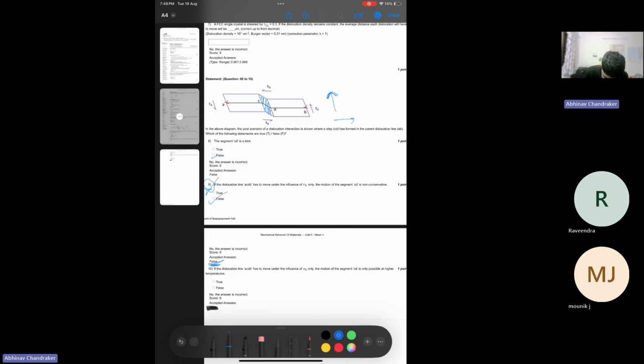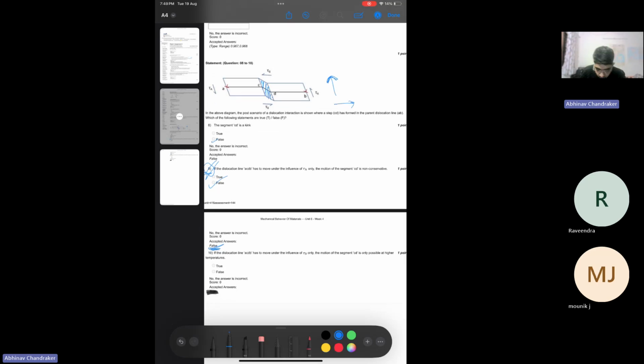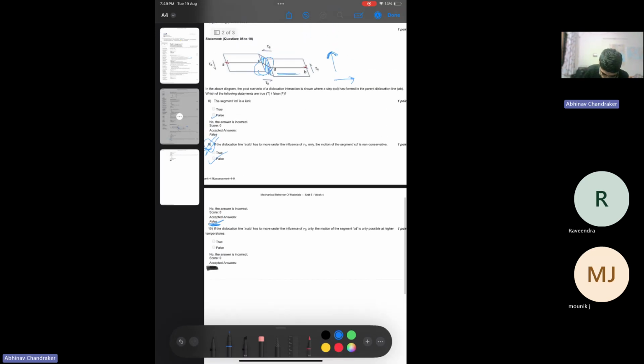Using the same logic, if the strain is along tau B, the component of the Burgers vector along tau B will be important, and that will not fall on the glide plane. It will be parallel to DB, right? Which is not on the glide plane. So for the portion CD, the movement will be non-conservative since the component of the Burgers vector along tau B is not on the slip plane containing CD, while for tau A it was on that slip plane. So the correct answer is true. I guess that can make sense.